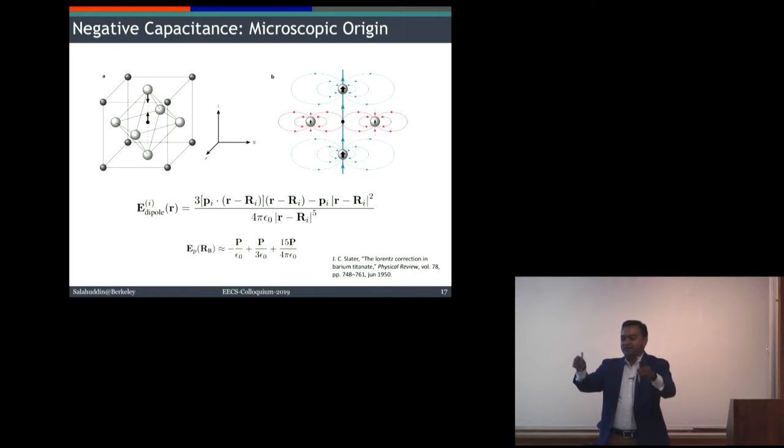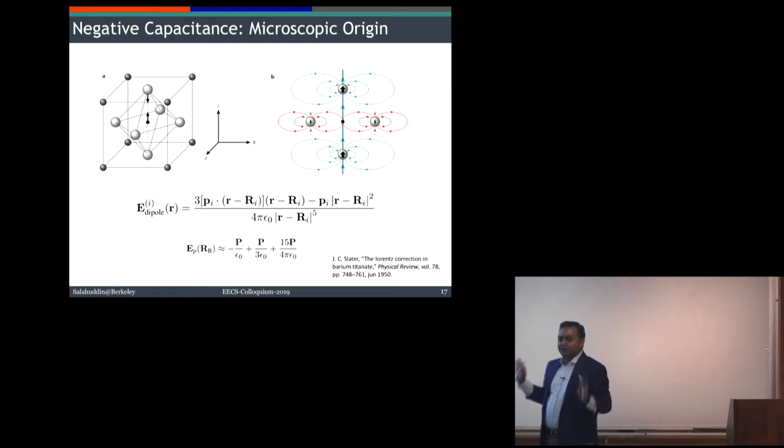If you have dipoles, then electric fields are coming out, and they will interact with each other. So if I look at one atom, I know how to calculate the electric field on that one atom. It's just the dipolar interactions. So I can write down this dipolar interaction equation. This is also very well understood, very classical. And if you have a computer, you take a ferroelectric material, put in your atomic coordinates, and honestly calculate this dipole over the lattice, you actually get the right result.